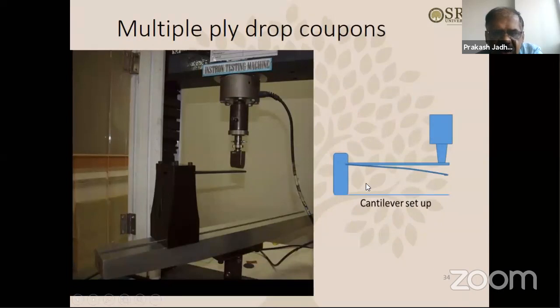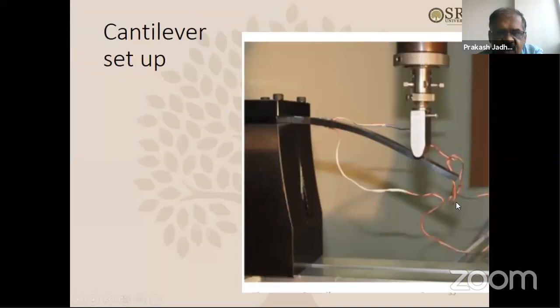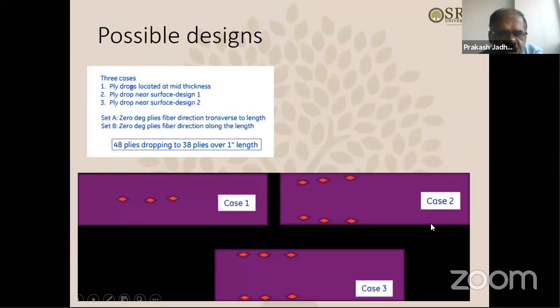Yeah, so a cantilever kind of setup was used. This is the first picture of the setup, a special fixture. What we did is we took that bending fixture stand and installed another fixture there, which can hold up the specimen and then bend like this. And application of load is achieved through this wedge-shaped fixture here, which applies the load on the specimen. So this is another picture of the setup. This one we talked about.